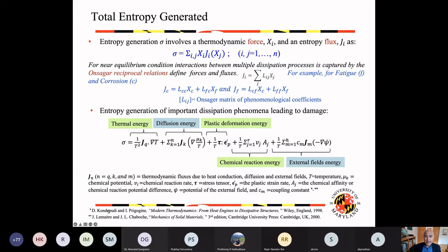Later on, actually, and this is very important, Lars Onsager, a professor at Yale, who received the Nobel Prize in Chemistry for this finding, said that there is a reciprocal relationship in this J, and found this relationship of J as a function of X. He defined it this way: J of, for instance, corrosion is a function of an L, which he defines as the Onsager phenomenological coefficient, which can be calculated experimentally, of the force of, let's say, corrosion and the force of fatigue, if this is fatigue and corrosion. These L's are coefficients which essentially should be found.